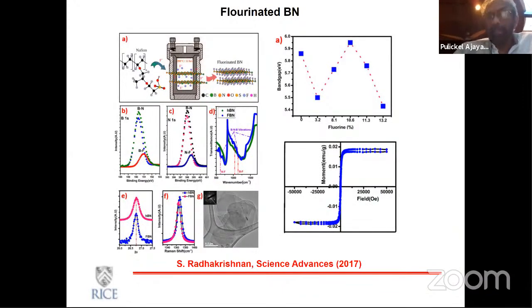A more difficult material to kind of chemically modify is boron nitride, which is a very unreactive system. But recently, we have been able to do this. There's a bunch of other groups that have also accomplished boron nitride. But fluorination in particular has been interesting for us. Again, this is a technique that we published some years ago on kind of a chemical way of fluorinating this. Recently, we have started to do some vapor phase fluorination, and addition of fluorine to boron nitride creates some really interesting structure. Again, there's hardly anything in literature, but they also show some properties like magnetism, at least slight amount of magnetism in this kind of material.